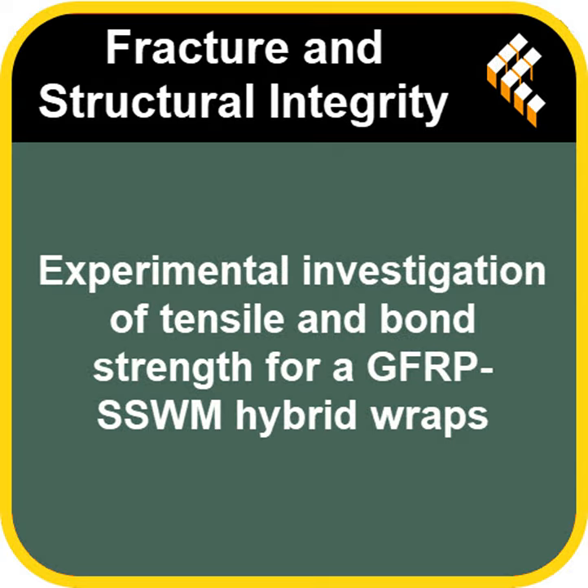Let's talk tensile performance first. Strength, stiffness. Right. So no huge surprise here. The highest ultimate load and stiffness came from the pure GFRP samples. GGG, that's 3 layers of GFRP, and GG, 2 layers. Makes sense. GFRP is the strong stuff. Precisely. And conversely, the lowest strength and stiffness were in the pure stainless steel wire mesh samples, SS and SSS. SSWM isn't primarily about tensile strength.